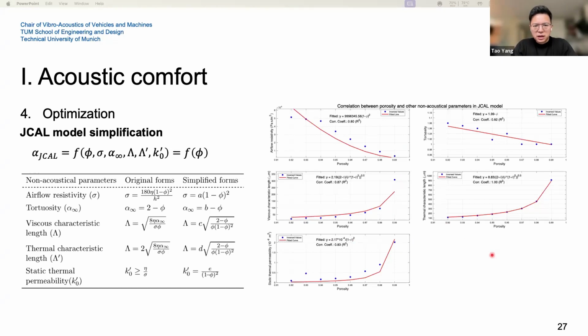So then, what idea came to my mind. I simplified the JCAL model from 6 parameters to 1 parameter. For example, it required airflow resistivity and so on, and in the end, I only use the porosity to predict the surface impedance and sound absorption of the porous material. This is because if we use the same fibers, the empirical or theoretical models for such acoustic parameters are all related to the porosity and the fiber diameter.